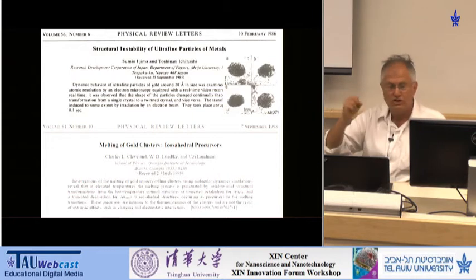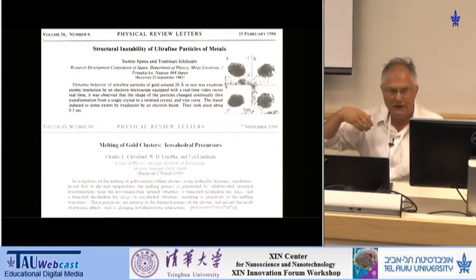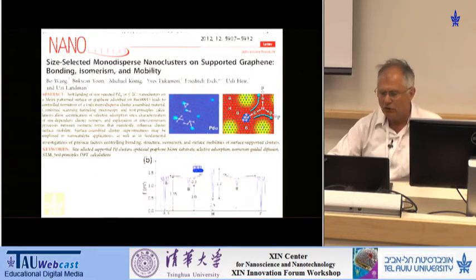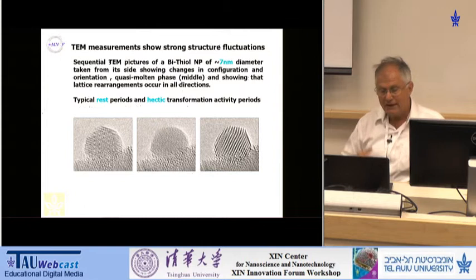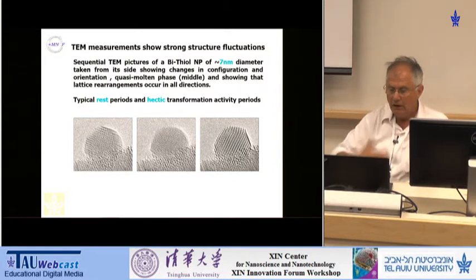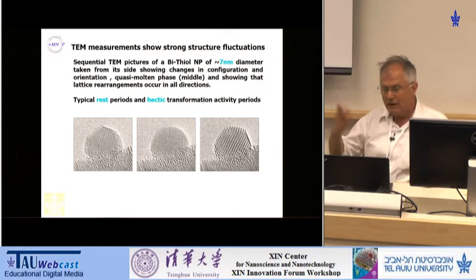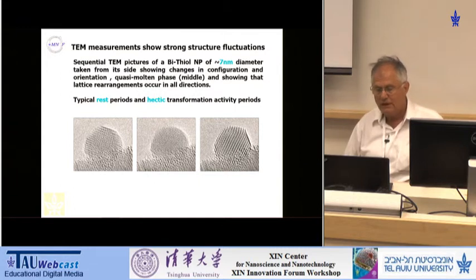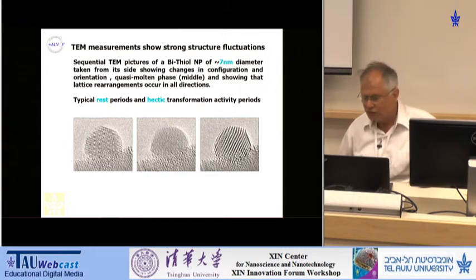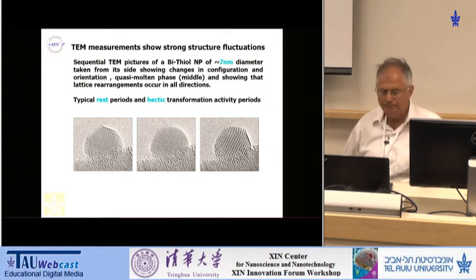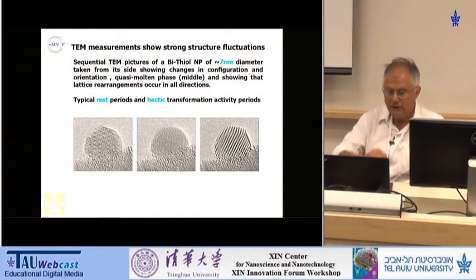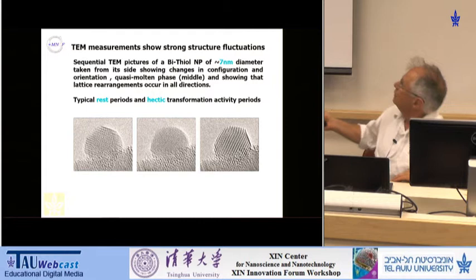The fact that small particles, less than 1 nanometer, that have several hundred atoms, are unstable has been known for about 20, 30 years, but it's the first time that one has observed that a particle which has 7 nanometer diameter, which contains many, many thousands of atoms, is still unstable. And that was first observed in TEM pictures of such particles. It turns out that they are quite non-stable.